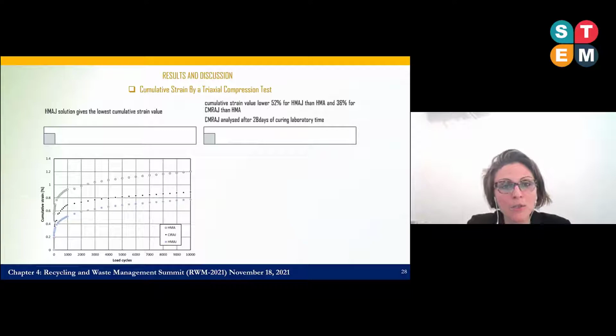So in terms of the triaxial compression test to evaluate the deformation, we can see that the hot mix asphalt with jet grouting waste gives the lowest cumulative strain value, reduced by almost 50% relative to traditional hot mix asphalt, and almost 30% for cold recycling of old milled asphalt with jet grouting waste relative to the traditional one. Of course, the value for cold recycling of old milled asphalt with jet grouting waste refers to the 28 days of curing time.